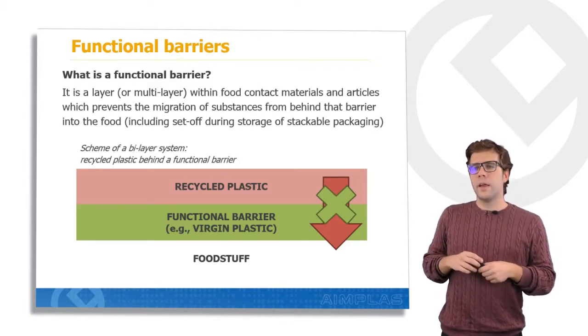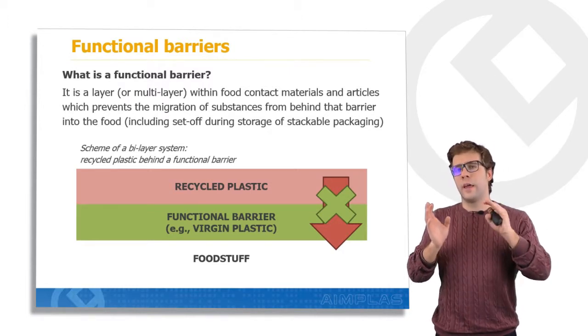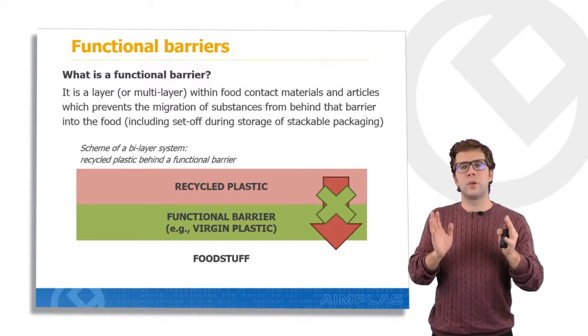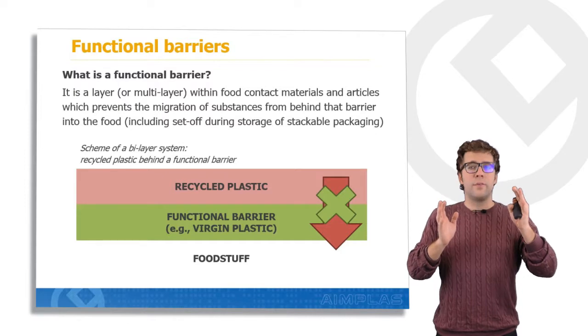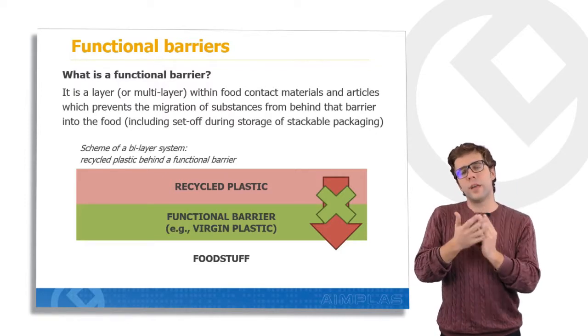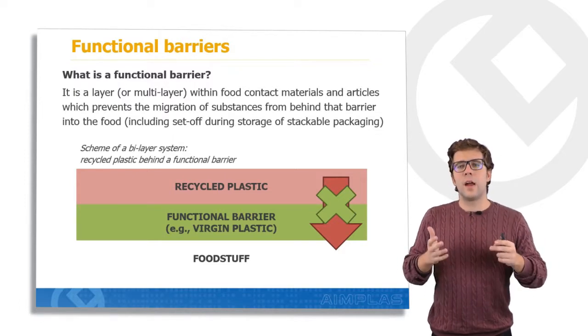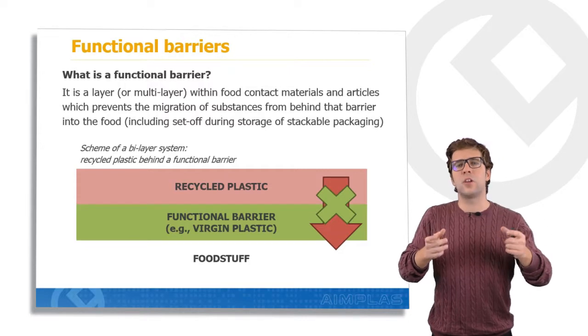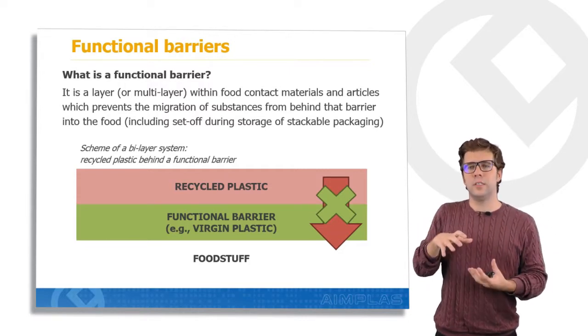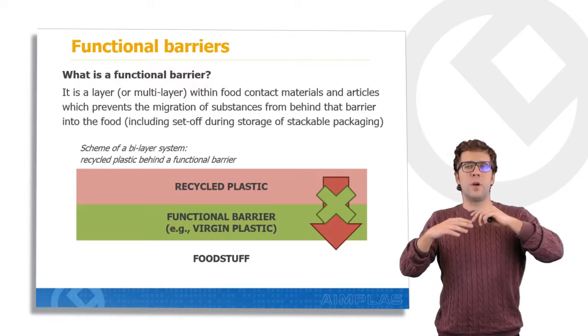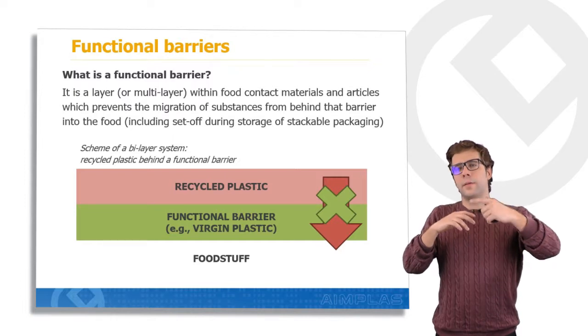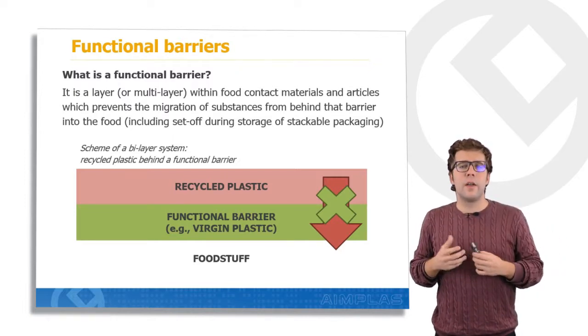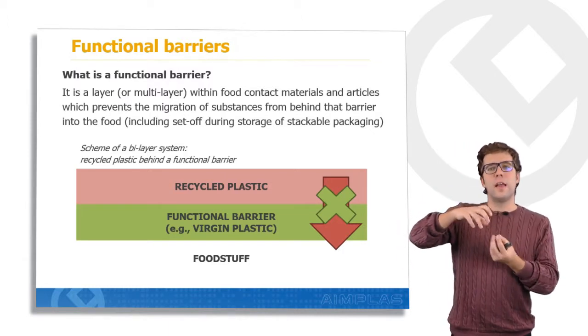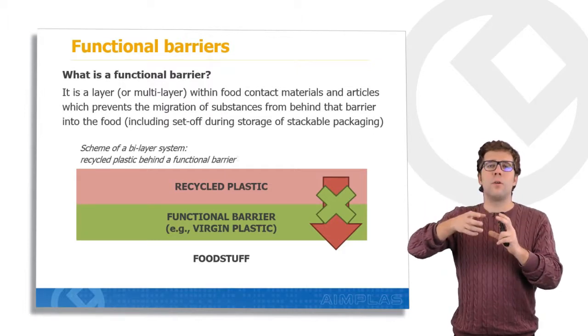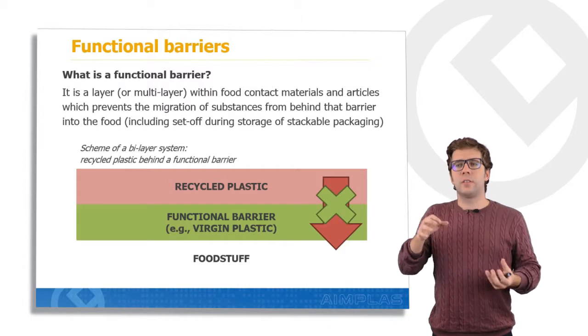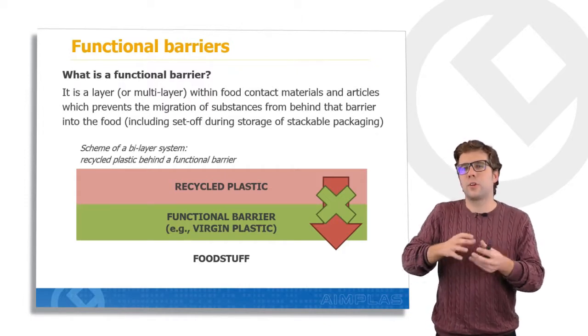Note that we can also use a symmetrical multi-layer structure with two functional barriers in the outer layers and a recycled layer in the inner layer. In this case, the symmetrical structure could also be used to prevent set-off effects in the case of stackable packaging. For instance, we can prevent the migration of the recycled layer in films, or we can prevent the migration not only to the foodstuff but also to the inner layer of tea cups, for instance, when they are stored in stackable packaging.